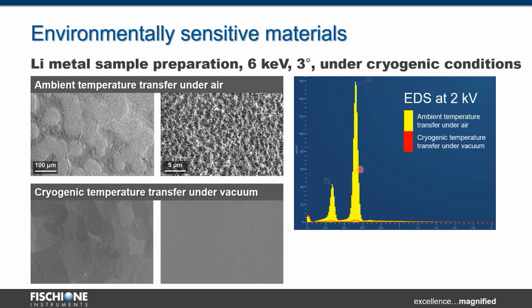The oxygen and carbon drop to zero level, as you can observe from this EDS collected at 2 kV, so collecting the signal from the very surface, so no contamination, nothing. You can just see at low magnification the grain structure of lithium metal, and then if you zoom in, you see only the gray color. What do you see?